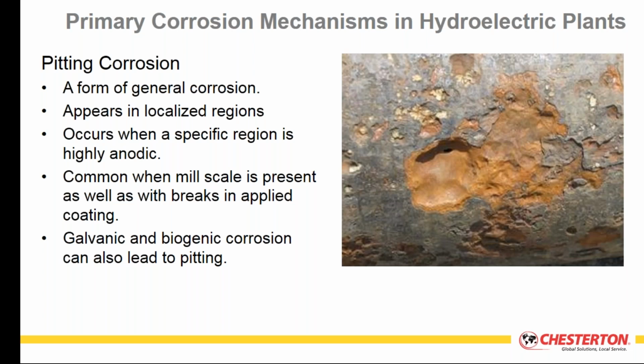Here's an example of what pitting corrosion looks like. You can see the associated scale on the surface, and where that scale has been removed, the new area has become exposed. That's the anodic region. At the bottom of that anode, you can actually see the hole penetration through, and that's a piece of 9mm plate steel, so that's a significantly reactive pit there. It's probably in the range of about 12 millimeters across, so roughly half an inch across, and it's about 9 millimeters deep, so about 3/8 of an inch deep, right through the steel.